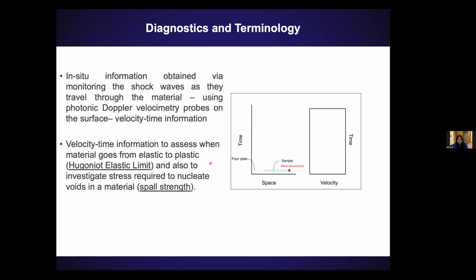For most people or most labs that do this type of work, the primary diagnostic is photon Doppler velocimetry. And what that is, simply speaking, is you shine a laser of known frequency on the back surface of a sample. As the sample starts moving, there's a frequency shift. Knowing that, and once you measure that frequency shift, you could do a Fourier transform and essentially get the velocity at which your sample is moving.